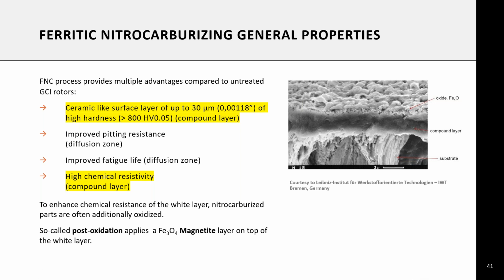On top of this compound layer or white layer, you build a layer of oxide. It's called Fe3O4, which is basically magnetite. It is a compact oxide which prevents corrosion. It may be very thin, it may wear out relatively fast. However, it protects discs from the onset from corrosion and helps maintain the quality of the disc during the whole lifetime.